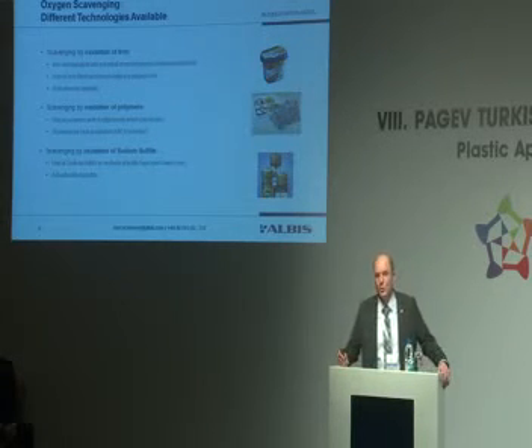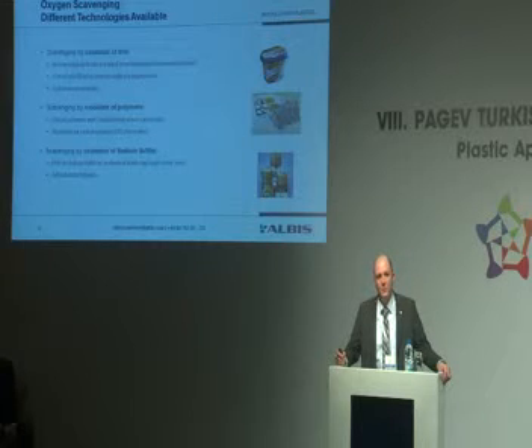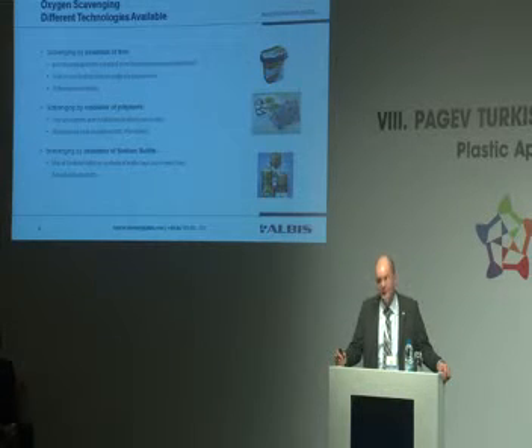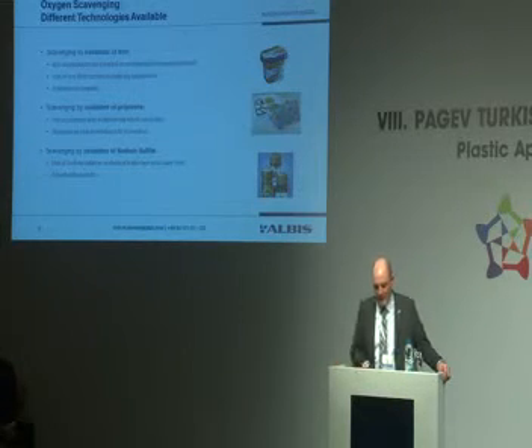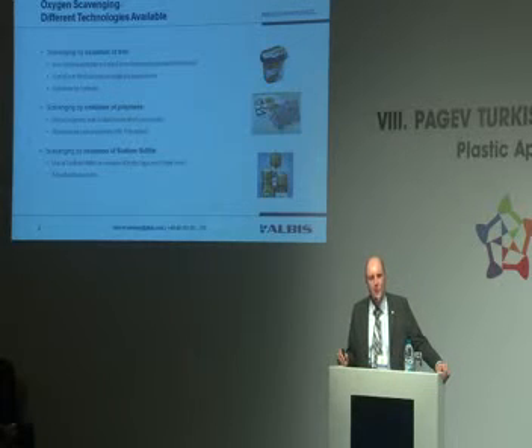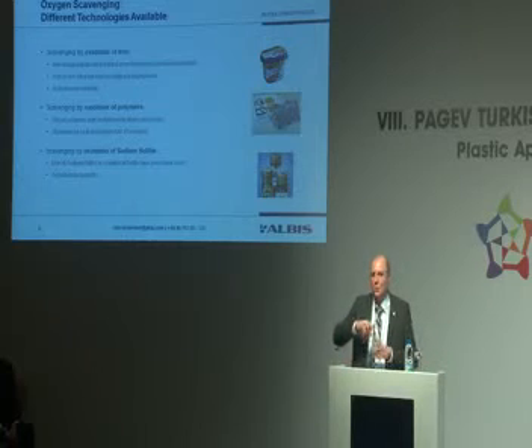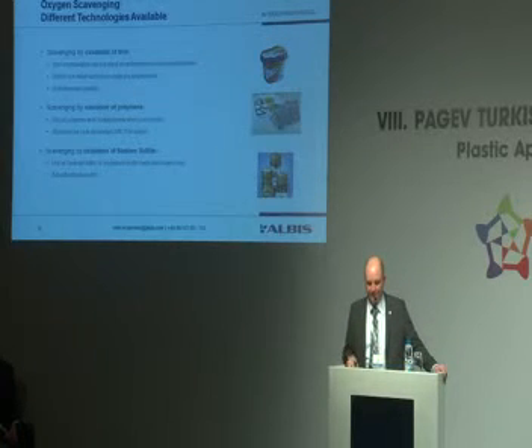Then we have oxidation of polymers. So you can use polymers that carry a lot of double bonds, so that are highly unsaturated. And these double bonds can open and in this way absorb oxygen. This mechanism is mainly activated by UV or peroxides. And then you have the scavenging of sodium sulfite. Sodium sulfite is highly hygroscopic and would transform upon uptake of oxygen. This is used very often in screw caps, in crown corks, in the bottles industry.